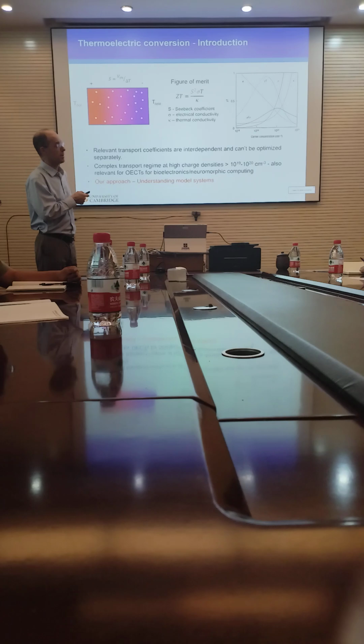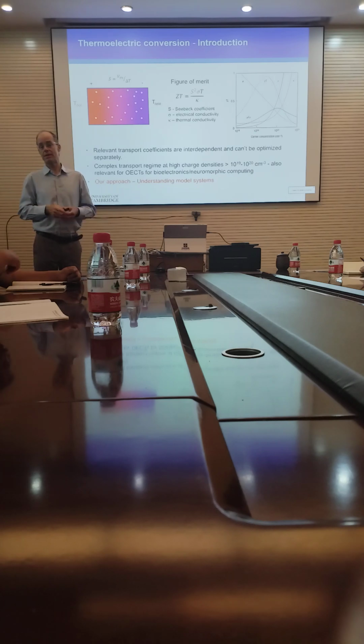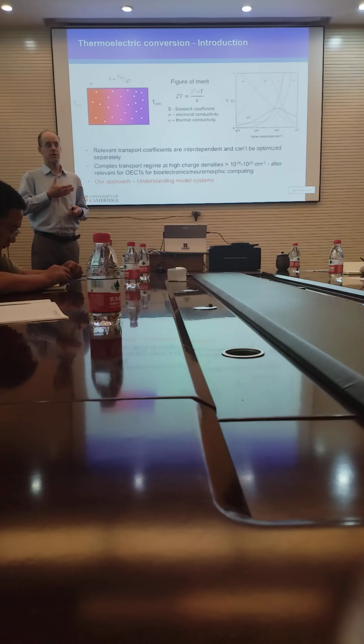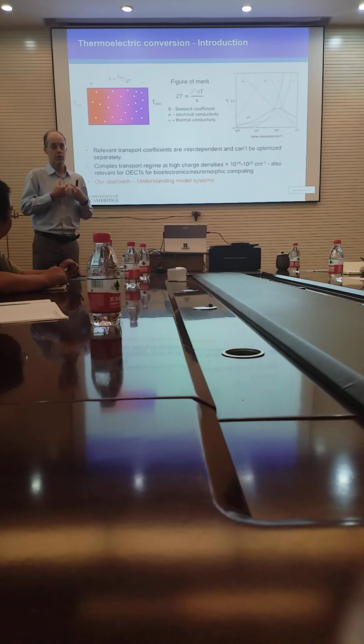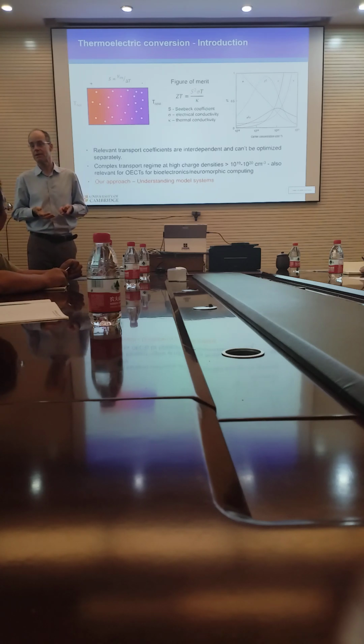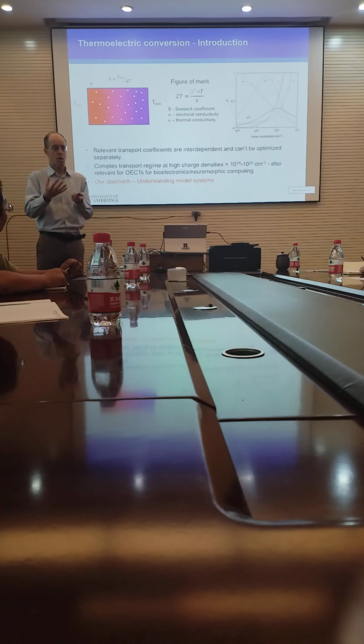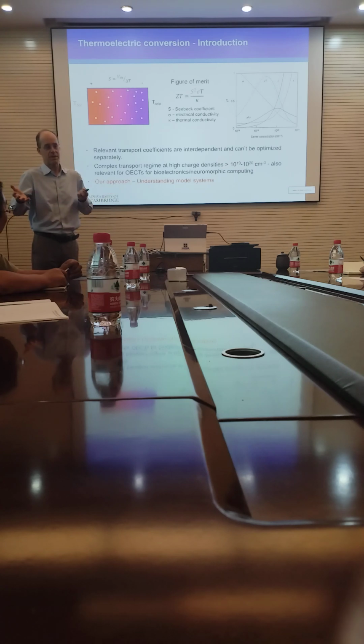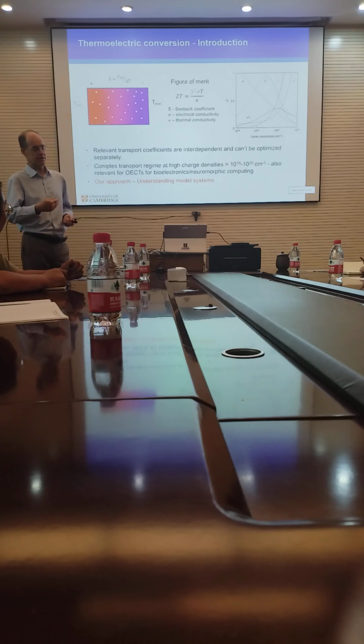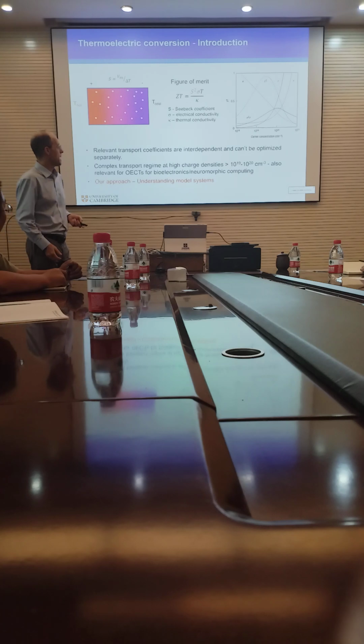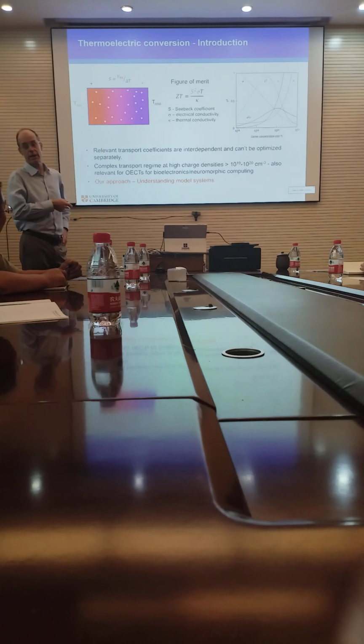And also kappa tends to increase with carrier density, because as you make the material more electrically conducting, also its thermal conductivity increases. You all know this. You know that copper, for example, is a good thermal conductor, and it's very difficult to make good electrical conductors that are thermally insulated. And so what people typically do to optimize their zT is to carefully tune the carrier concentration and find the point at which that zT is maximized.